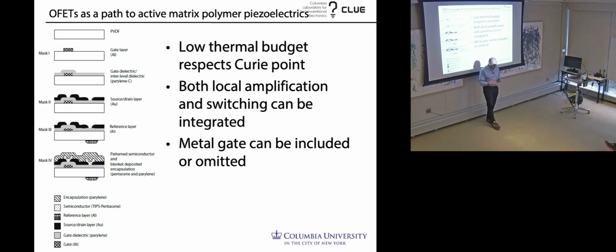But in a kind of a parallel process with only one extra step, we can also make the transistor I show on the right. And you notice that that transistor doesn't have any gate. And instead, it's gated by the charge that we have in the PVDF. And so when we strain the PVDF, we get a charge here, and then the image charge that's formed on the channel then gates the transistor. And that has a number of significant advantages. It has much lower parasitic profile. It can also hold charge for a long time.